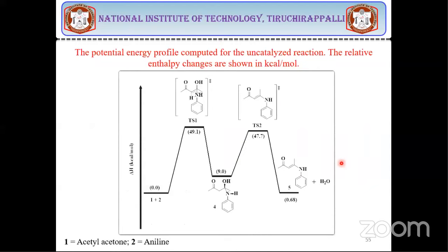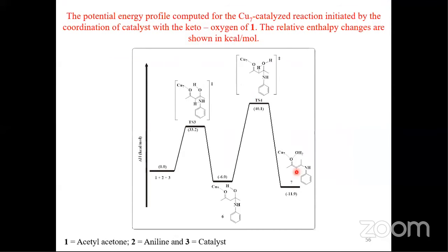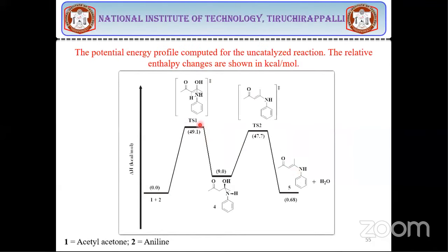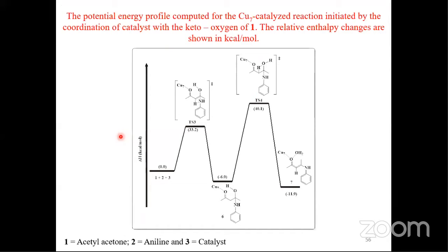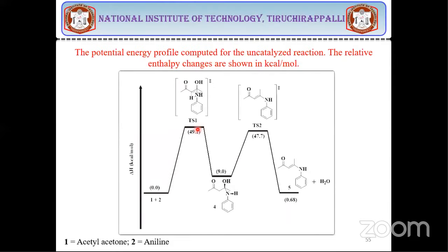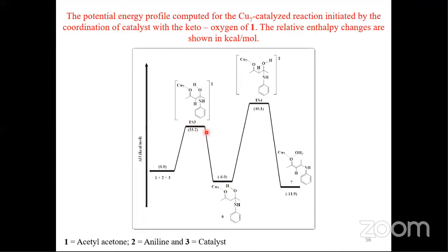And we have studied the mechanism of this reaction by means of DFT calculations. You see, this is the energy profile of the uncatalyzed reaction without copper on boehmite. This is with catalyst. Without catalyst, you see, the energy of the transition state is 49.1 kilocalorie per mole. But if we add a catalyst, the energy of the transition state comes down. That's why I said in the presence of the catalyst, the reaction proceeds through the pathway for which the energy requirement is less. So in the presence of the catalyst, the energy required to form the transition states is less. Without the catalyst, it requires high energy. With catalyst, it requires less energy.